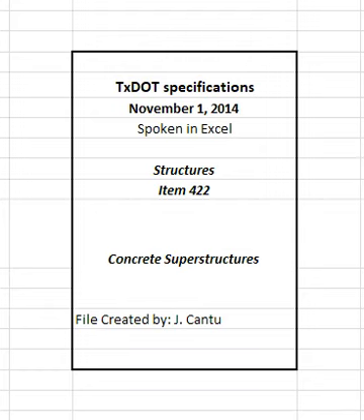Thoroughly clean the hardened concrete surface of all loose material, laitance, dirt, and foreign matter, and saturate it with water. Remove all free water and moisten the surface before concrete or bonding grout is placed against it. Ensure the surface of the existing concrete is in a saturated surface dry, SSD, condition just before placing subsequent concrete.